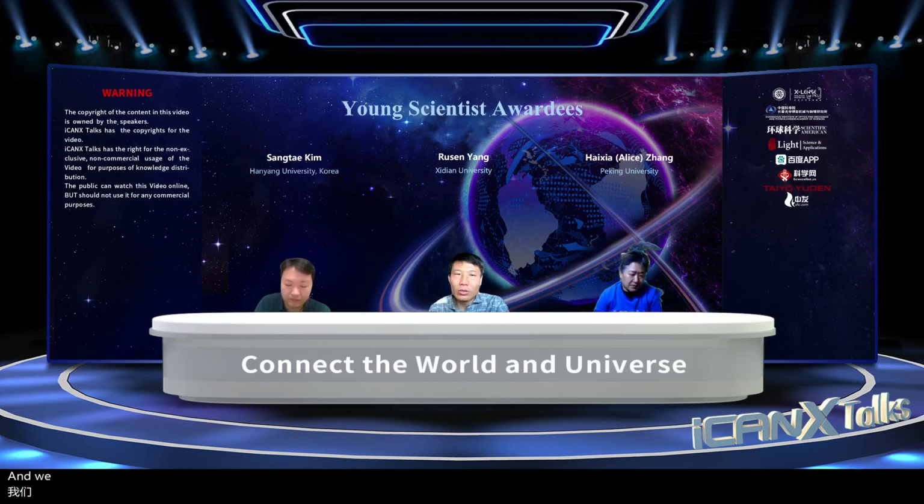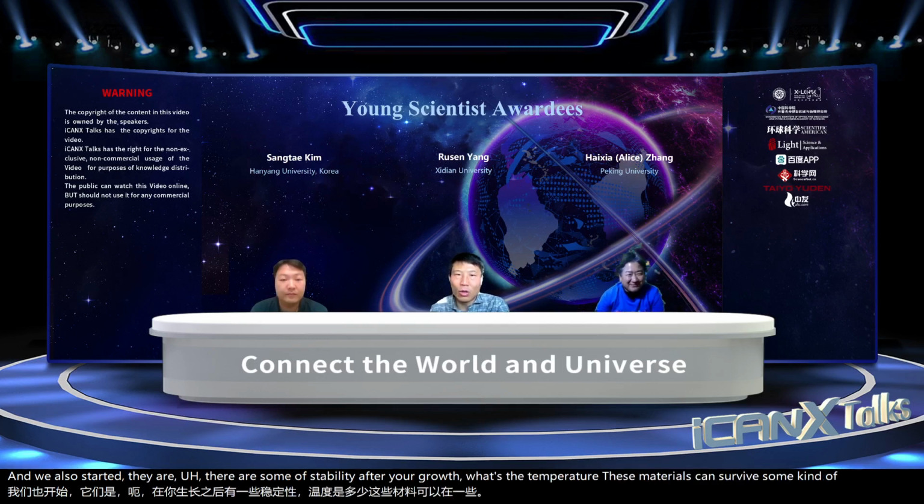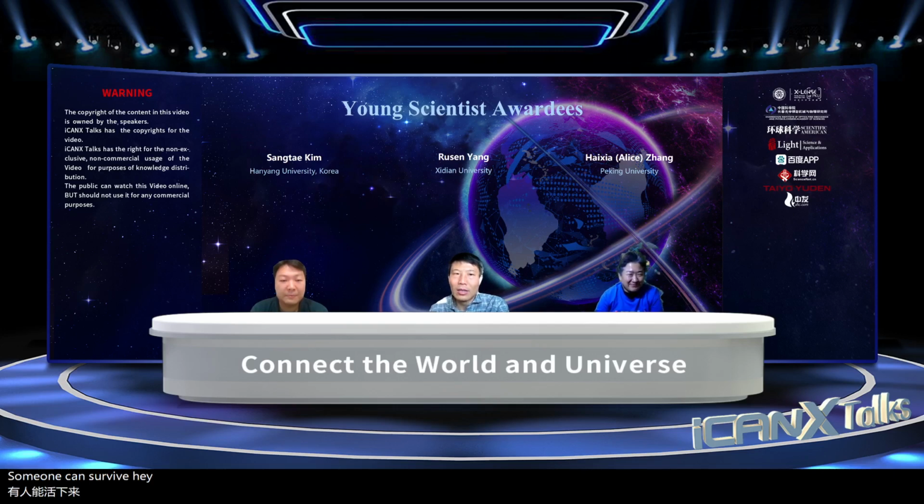And we also studied the thermal stability after your growth. What's the temperature this material can survive? Some can survive lower, some can survive higher. Some can survive even around 300 degrees Celsius, right? So some are really thermally stable, but some are not.